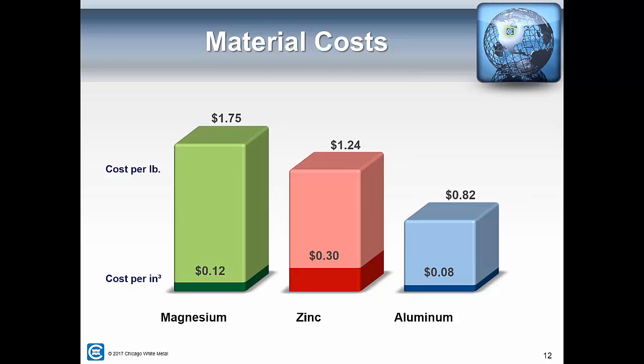But looking strictly at the three main families of die casting alloys, you can see that generally aluminum is a lower cost per pound. Market prices right now at 82 cents, but it's also a lower cost per unit of volume. I put a cost in here of 8 cents per cubic inch. The zinc price is $1.24 a pound currently. Translating that, it's a heavier material. It's 30 cents per cubic inch. And magnesium, though it's the highest price per pound, it's also the least dense material. And so when you translate that into a unit of volume, it's not far from aluminum, and it is much less than zinc. So magnesium sometimes gets a bad rap because of its higher price per pound, but it is really sold when you put it into a part on a per volume basis.